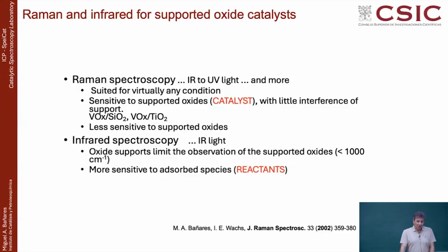From an unknown sample, it's difficult to tell because you never know. There are many problems. Some samples may give you fluorescence sometimes. I made spectra for a colleague in my institute. It was a catalyst of zinc oxide on graphene, and we were making a map with a green laser and with a violet laser. It was very interesting because with the green laser, we could very nicely see the graphene Raman bands, but the zinc oxide Raman bands were very weak. Then we made a map with the violet laser, and we could see the zinc oxide bands very nicely and not the graphene bands so well. So we had two maps, the green map and the violet map, and each one was used to discuss one or the other, while looking at the same area.